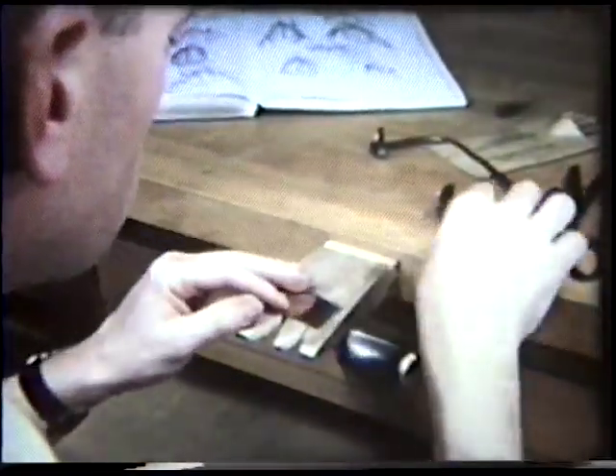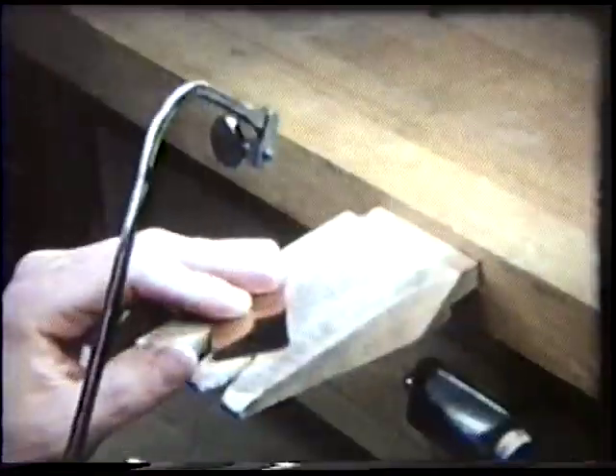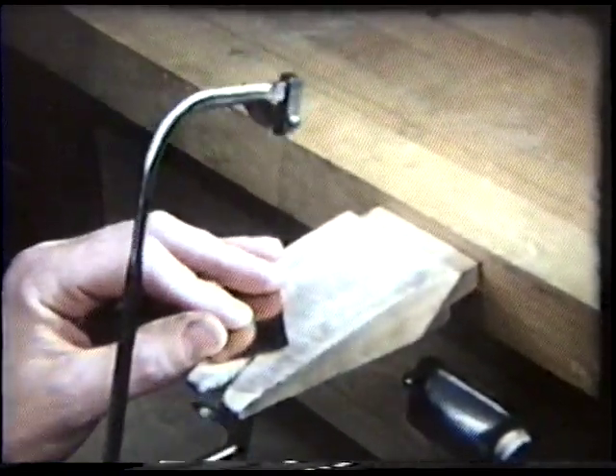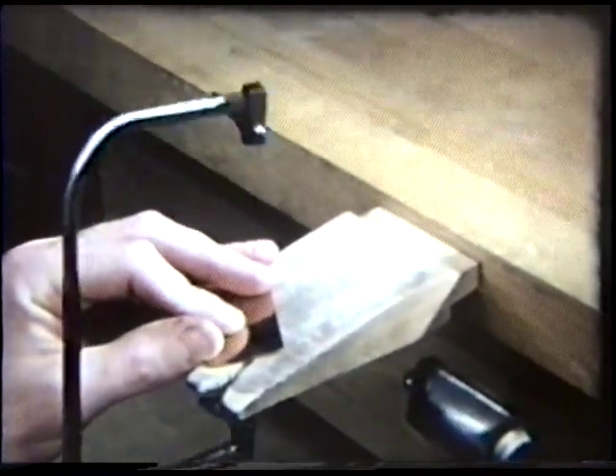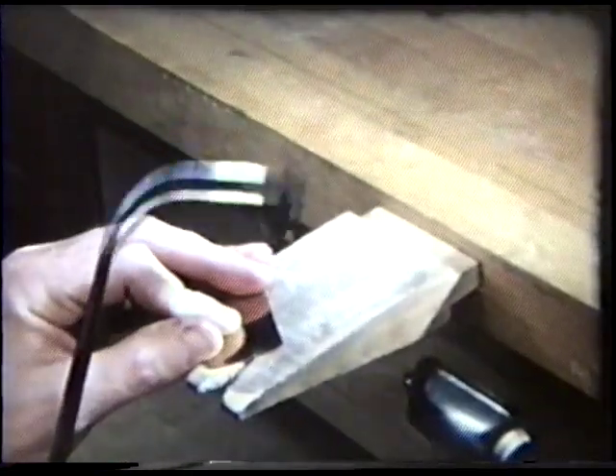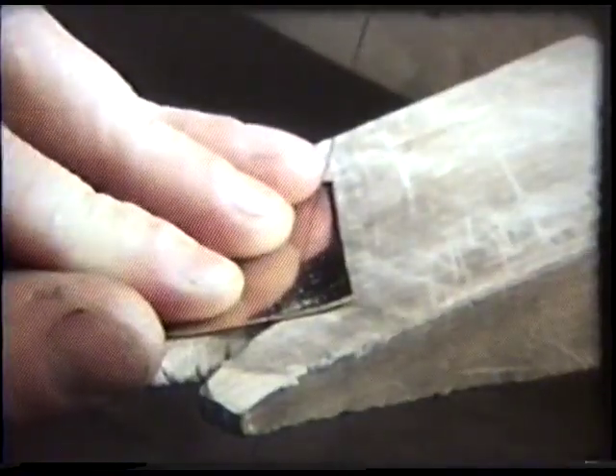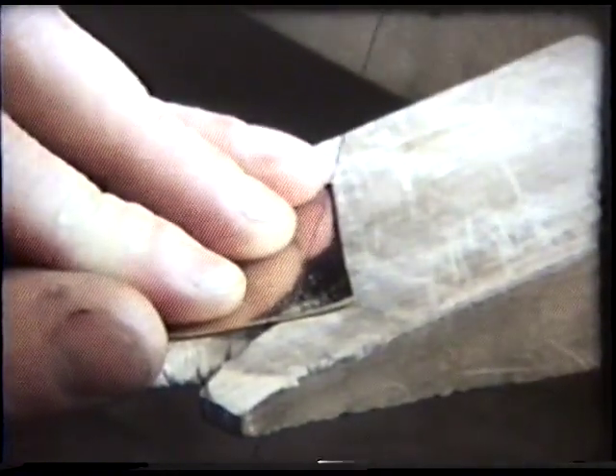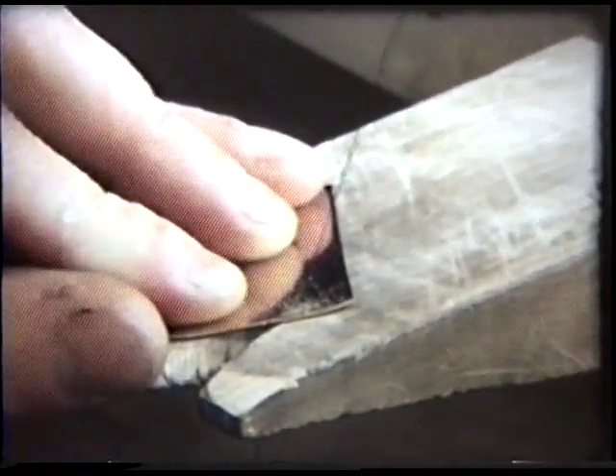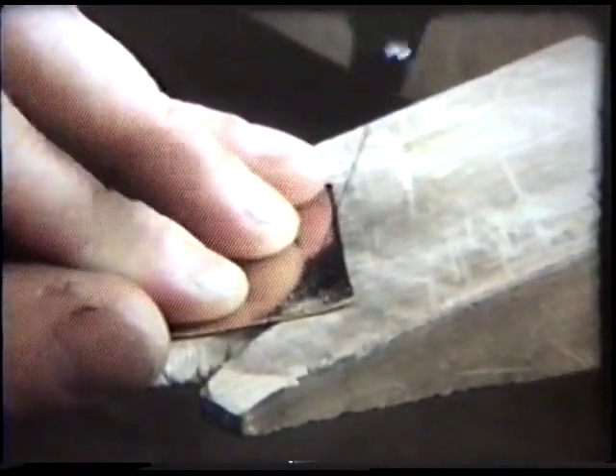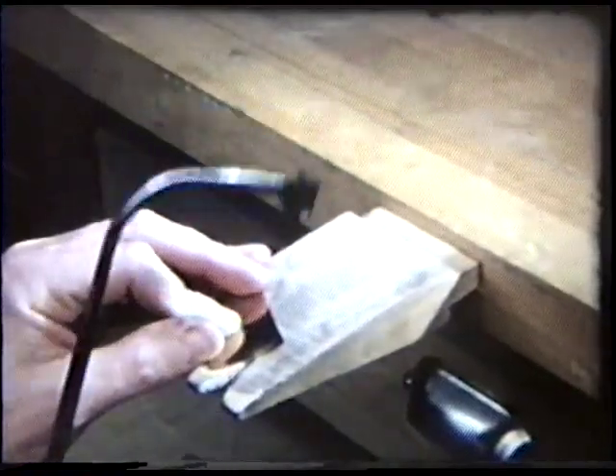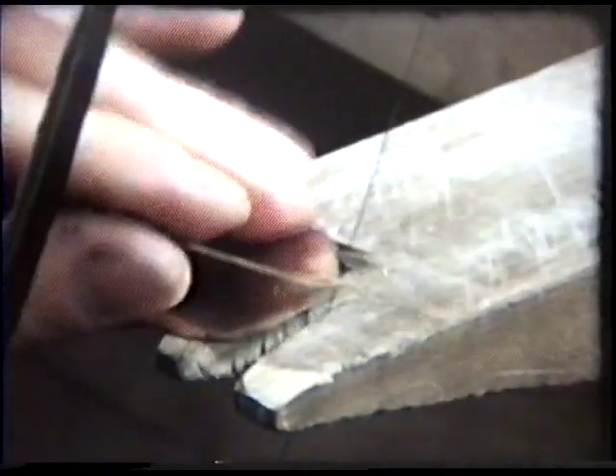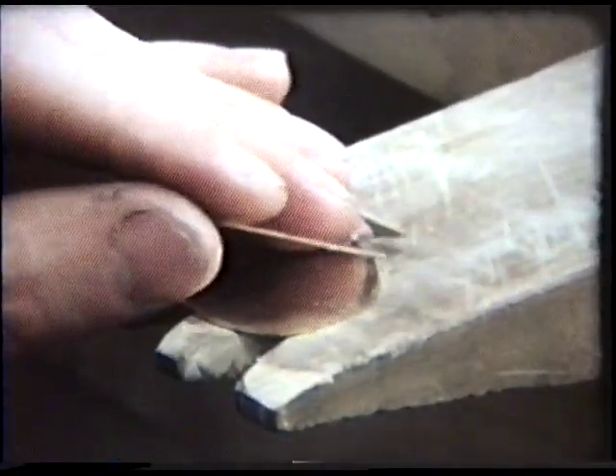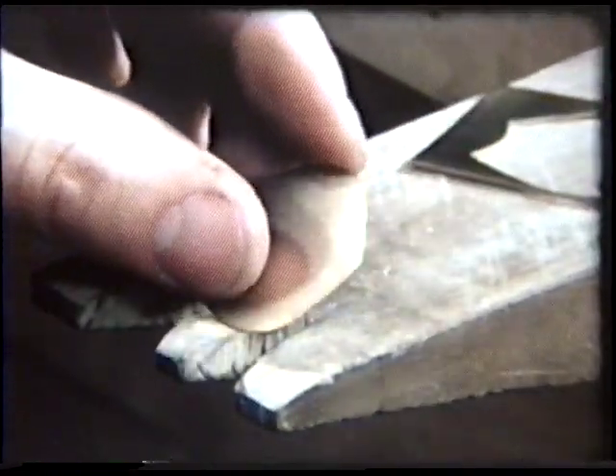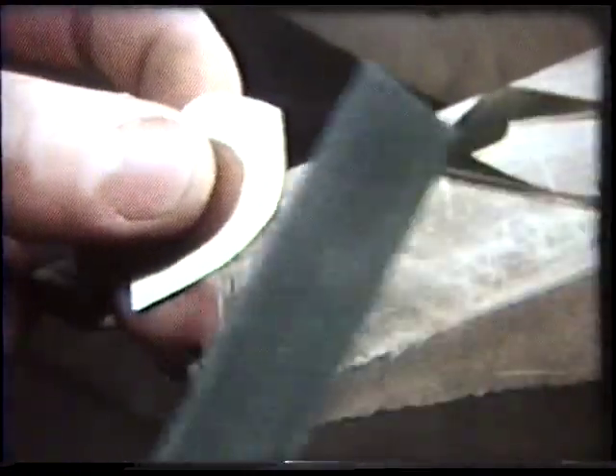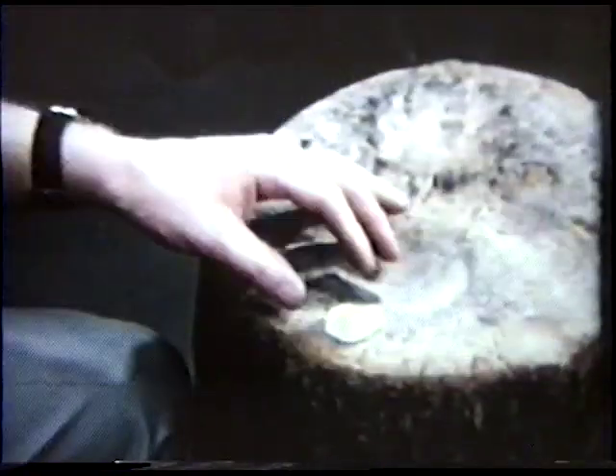The piece, which will form the back of the beetle, is begun by scribing the outline of the shape of the back on a sheet of 18-karat gold, which is a little less than 1/16 of an inch in thickness. The shape is cut from the gold with a jeweler's saw. The saw cuts as the blade is drawn vertically through the metal, and only enough forward pressure is used to keep the saw against the metal. The slightly roughened edge left by the saw is removed with a file.